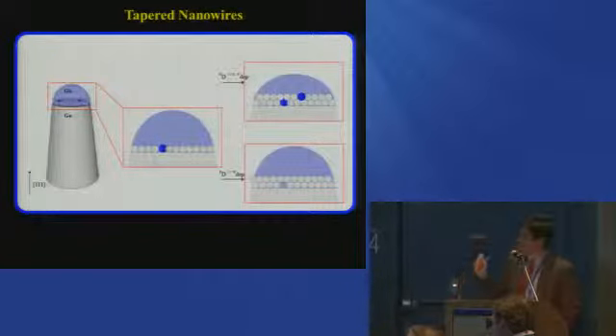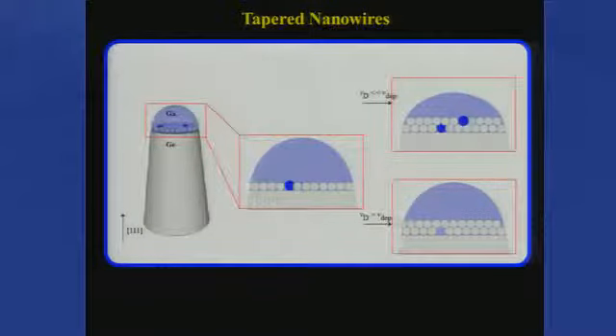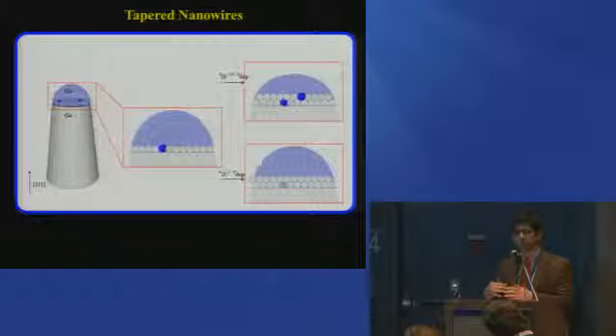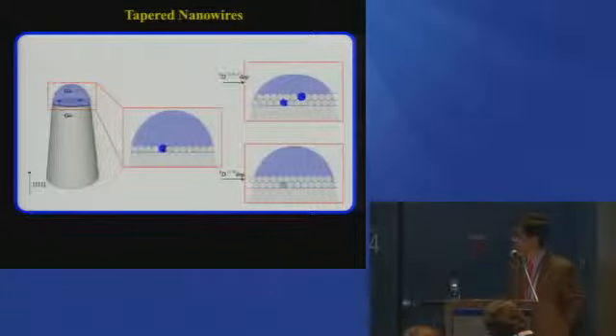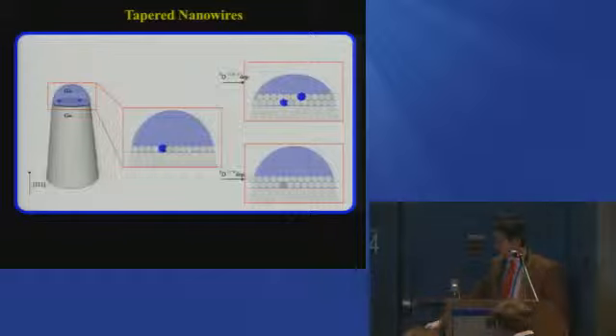One thing I'll mention that everyone always asks me, so I'll cut it up front. In this sort of embodiment, these germanium nanowires, they're tapered. And they're tapered because as you're growing, a little bit of gallium is getting left behind in the crystal growth front. And from a practical standpoint, that means you have some gallium impurities in the wire, and they're also limited in terms of how tall they could possibly get. We've been trying to figure out ways around this.